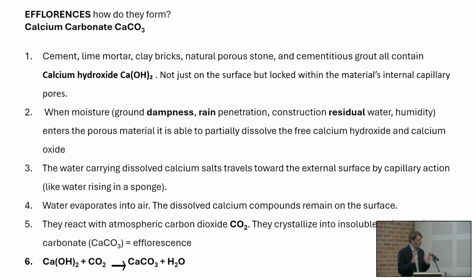No, we don't have a problem with cement. This is normal, very normal. The problem is the dampness, is the water. Because if you have much more water than what is required by the cement compound, the water in excess, evaporating, will bring the calcium hydroxide on the surface of the flooring or the wall.